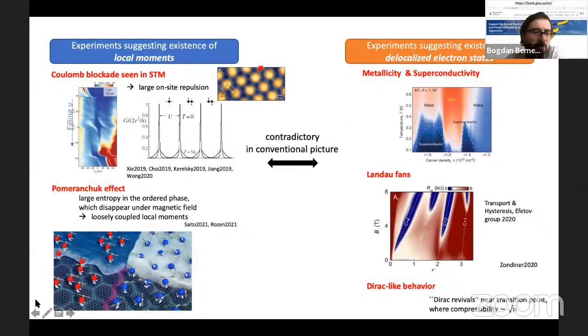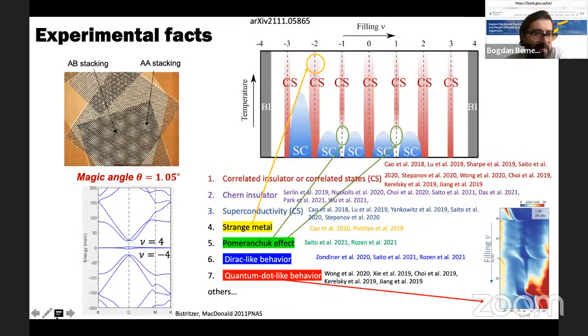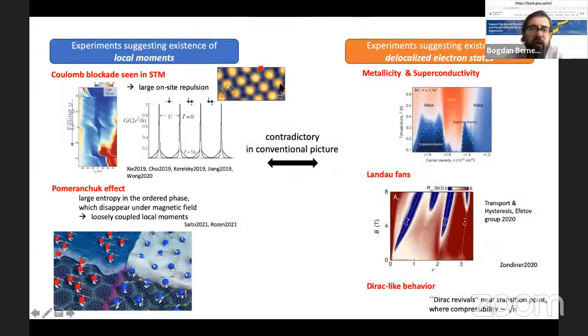Moreover, in kind of two large classes, the experiments in this field can be characterized by the following juxtaposition. Some of the experiments see quantum dot behavior. So, for example, if you do STM, as I said, you can see a highly localized charge at the AA stacking of a twisted bilayer. So the AA stacking would be actually the center of this hexagon. So this is the AA stacking here, and the AB stacking would be this. So we're going to call these two regions the center of the hexagon, the C6 invariant, AA stacking, and AB stacking is the C3 120-degree rotation region.